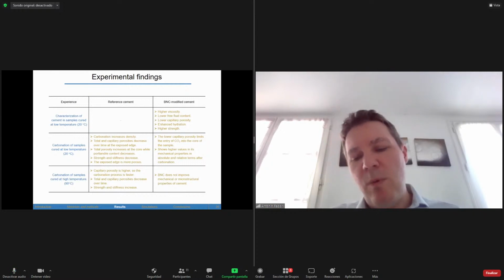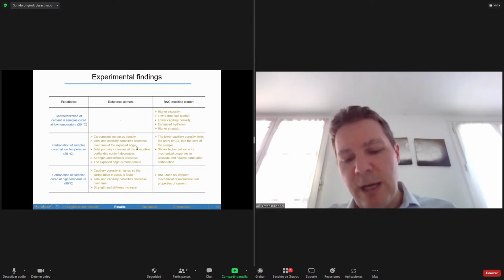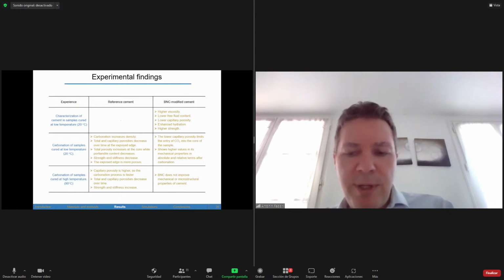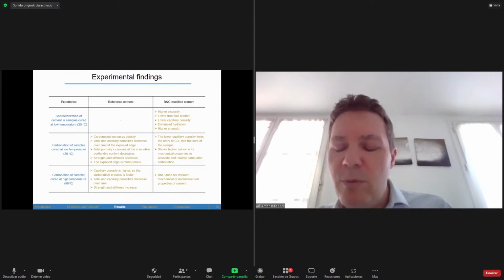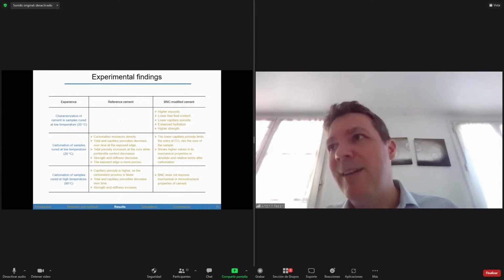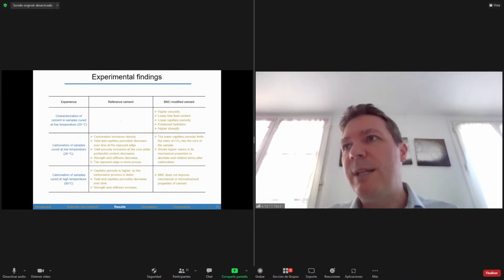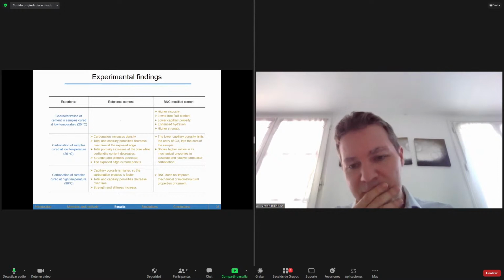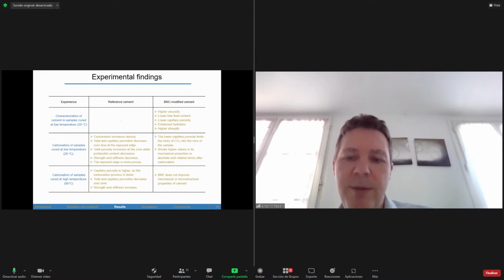Yeah, but in that way you got one situation where the samples were never dried, and the second one where you make hardening at higher temperature, then you dry the sample and resaturate it. Why didn't you test the case where the hydration is made at higher temperature but with no drying? Yes, that was mainly because we considered some experiments from the literature, and the other reason is that we wanted a really porous material in order to have a fully carbonated material after the process, but mainly from the literature.